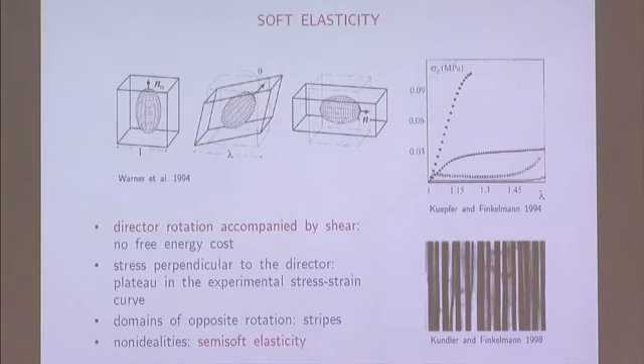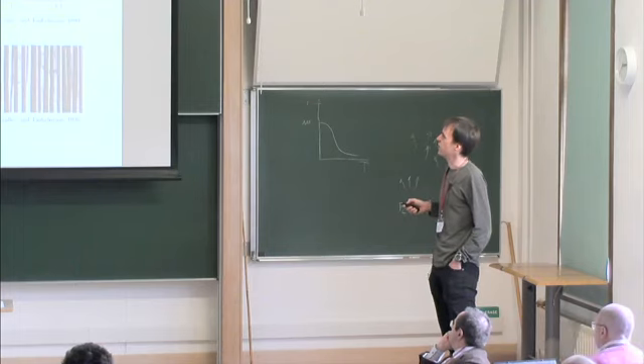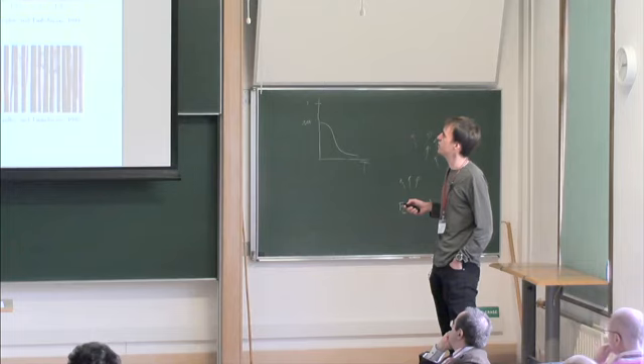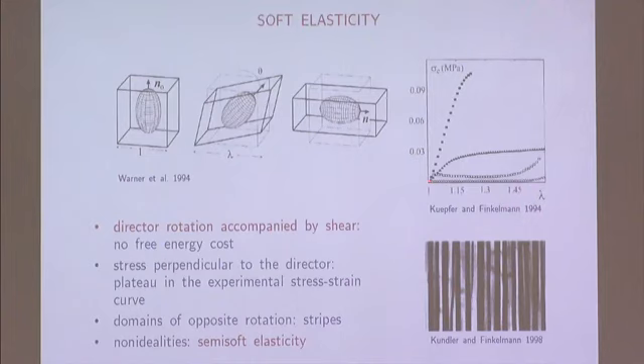And there are also, of course, experiments. One can try to probe this soft elasticity by applying stress, now not along but perpendicular to the existing director. Some of the stress-strain isotherms are shown here in this plot, and you can see that at some point you reach a plateau where the system seems to deform softly at rather low free energy cost. And if you are dealing with a larger sample, what you can typically see is domains of opposite rotation, so-called stripe domains, that you can also detect optically, as here.